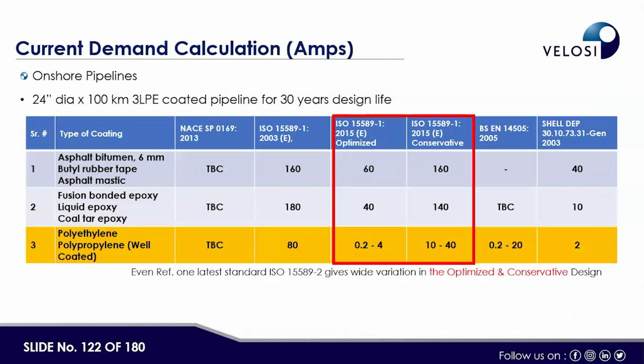If you have asphalt coated pipelines, as per ISO 15589, for a 30-year life it requires 60 ampere current. If we go with the optimized design, and if we go with the conservative design, it requires 160 ampere. So you need a transformer rectifier unit of 160 ampere to protect your asphalt or bitumen coated pipeline. But the same pipeline, if it is 3-layer polyethylene, will require only 10 to 40 amperes. So here we will calculate the current requirement. Next slide.